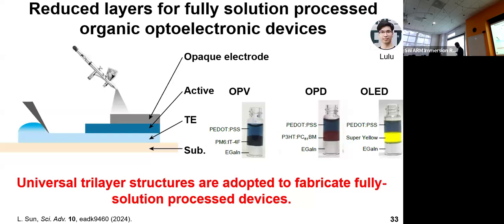All these three layers are fabricated using solution processes, blade coating or spray coating. And then we just simply change the active layer materials: PM6, Y6, IT4F for the OPVs, the P3HT, PCBM systems for OPDs, and the Super Yellow for OLEDs. And then the EGaIn and PEDOT:PSS, these two electrodes are used for all the different photo devices.